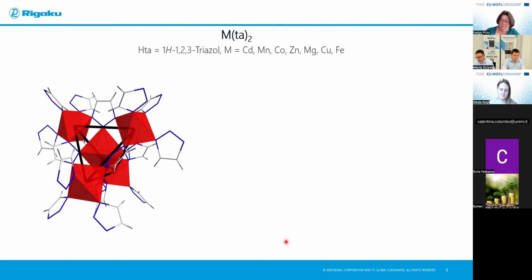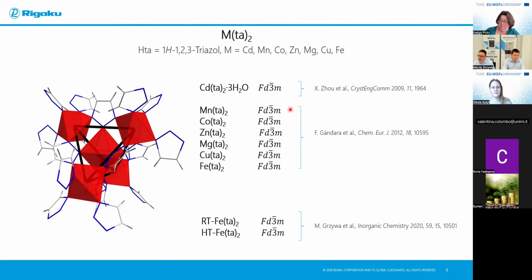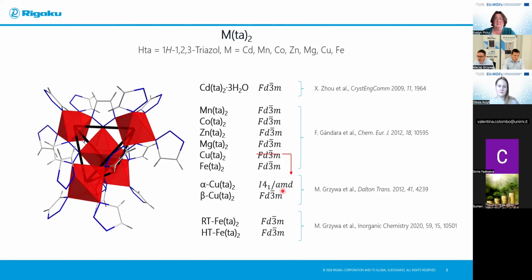Triazole-based coordination compounds have been studied since the early 80s. Several isostructural compounds have been reported. These compounds crystallize in cubic crystal system within the space group Fd-3m. In contrast to the isostructural compounds, copper triazolate, which contains Jahn-Teller active copper(II) centers, crystallizes in tetragonal crystal system. This compound shows reversible phase transition at higher temperature.